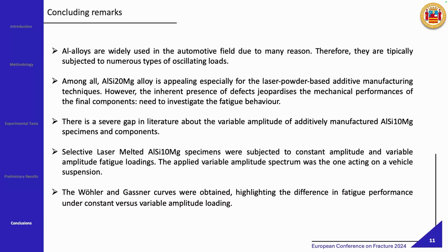But the main issue is that literature is still quite poor about the variable amplitude fatigue performance of this kind of material. And so we started an experimental campaign by testing specimens made in this alloy, obtained by selective laser melting, subjected to both constant and variable amplitude fatigue loadings. And we started highlighting the different performances that this material has, but the experimental campaign needs to be widened, and it will be in the near future.